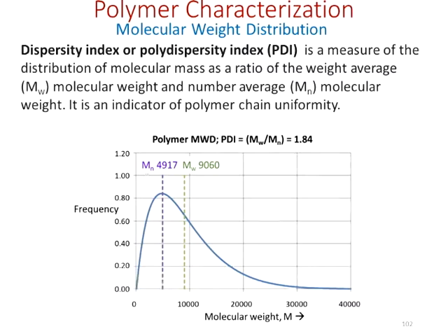So you take that MW divided by the MN, and in this particular polymer case, you get 1.8. That means that's not a bad distribution for a polymer. Now, for some solids, for very high precision work, you want that polydispersity to be about 1.2. So when you get a polymer at about 1.8, less than 2, you kind of call it quits. You call it a day. You say that's not bad.